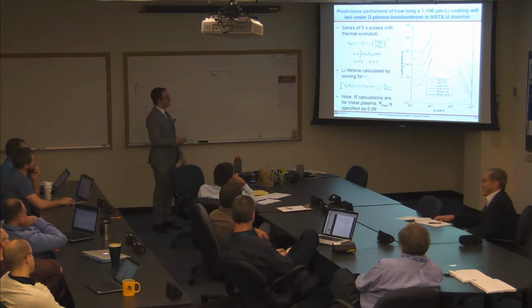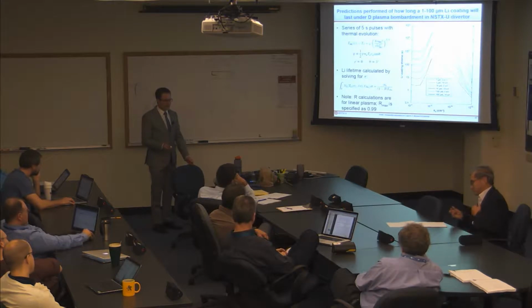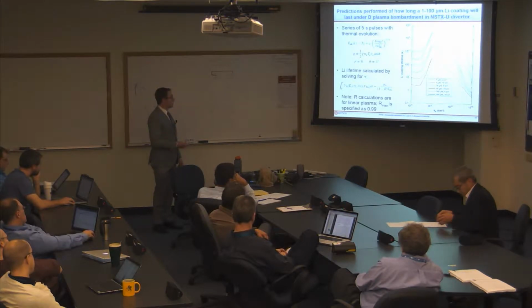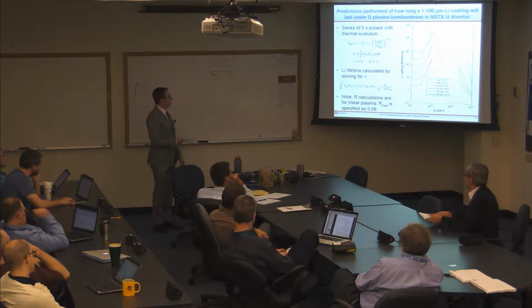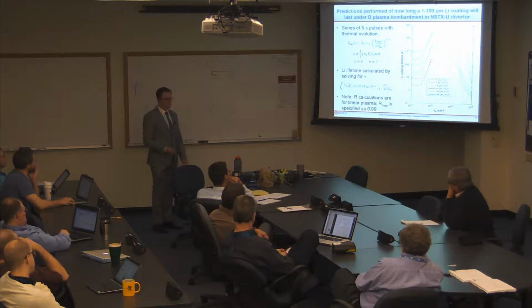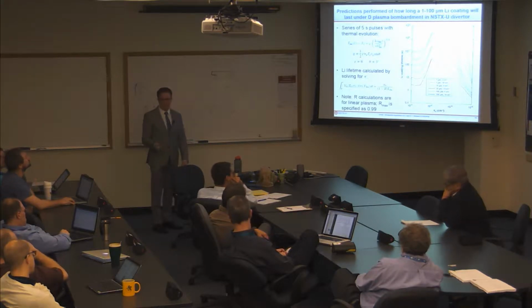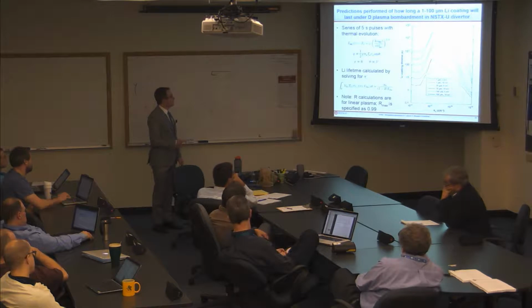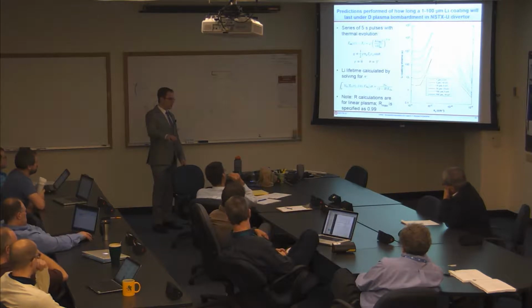So the way that you can actually predict this is basically do a simulated series of pulses. The predicted current flat top in NSTX-U is 5 seconds. So I did a series of 5-second pulses, and basically I assumed you had a thin lithium coating on a TZM molybdenum substrate.